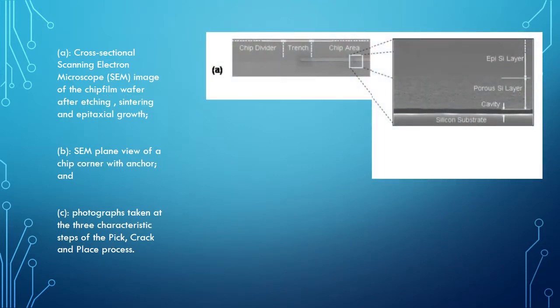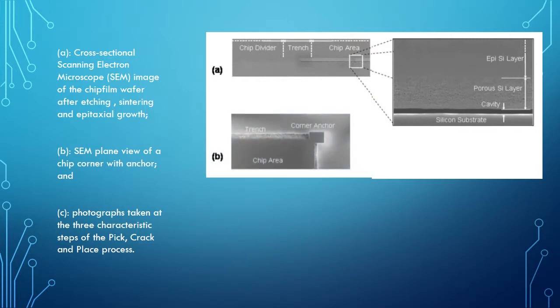In part A of this figure here, we can see the cross-sectional scanning electron microscope image of the chip film wafer after etching, sintering, and epitaxial growth. In the inset, there is the cavity left after sintering of the wafer. After the chips are trenched along the sides, only anchors are left at the corners so that they are weakly attached to the substrate.